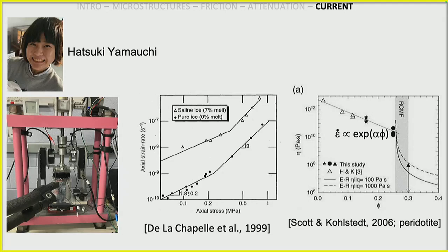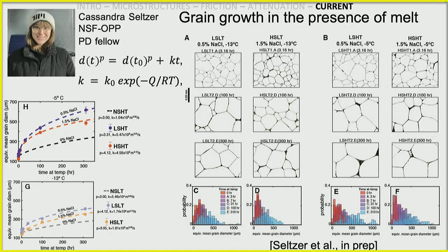Okay. Another study that we're working on, Cassandra Seltzer, she's an NSF postdoc fellow who came to our lab just less than a year ago, and she wants to study if you really shear an ice partial melt system, will it form a fabric, and in particular, will the melt form a distinct fabric in a really highly sheared sample? But before she does that, I was asking, well, what do we know about grain growth? You want to know what you started with, and what would have evolved just by it sitting in the experiment, and what evolved because you strained it.